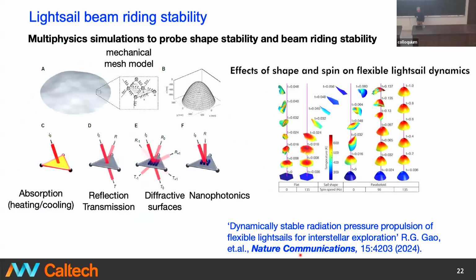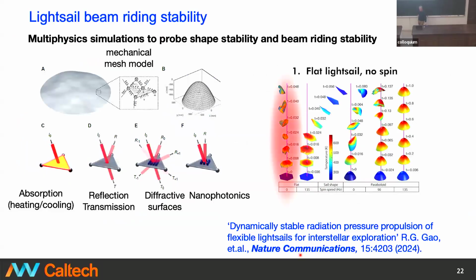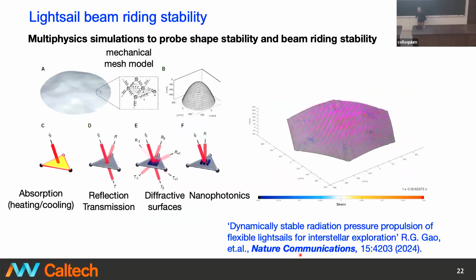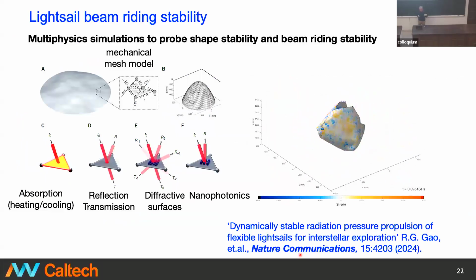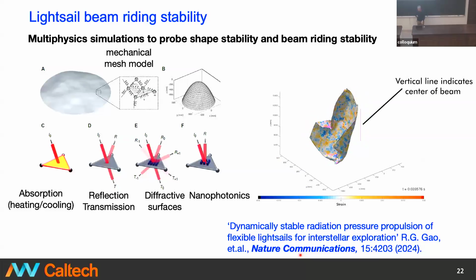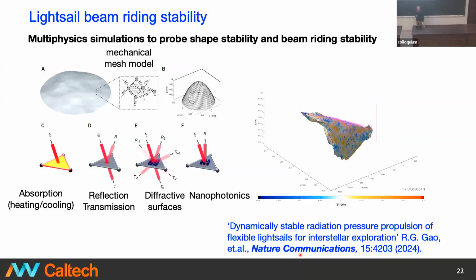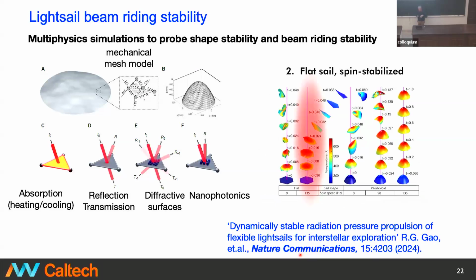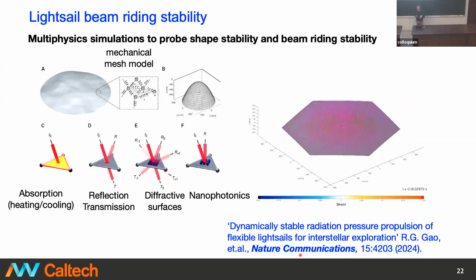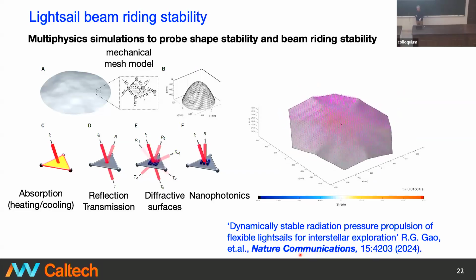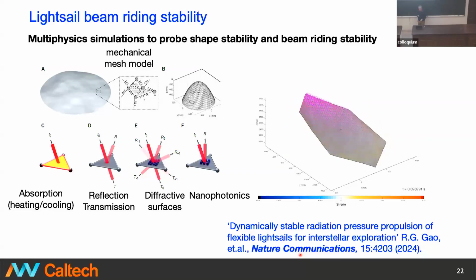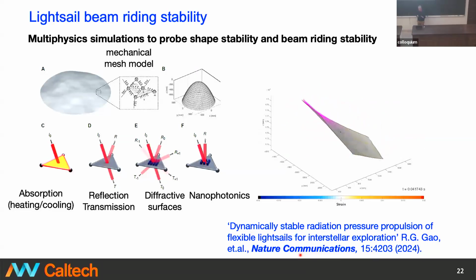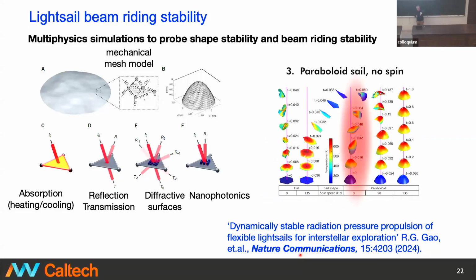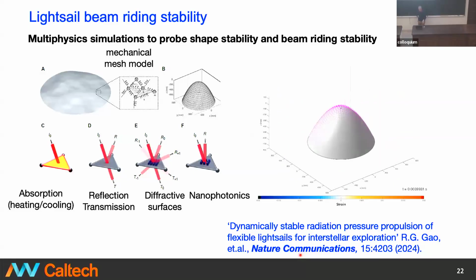So I want to say a little bit about beam riding stability. And to study beam riding stability, we developed a multi-physics simulation that takes into account absorption, reflection, scattering, and nanophotonic resonances. And of course, what we're interested in is materials that are thin membranes. And so if we simply illuminate, for example, the structure that I just showed you, or this flat structure, you can see what happens is it becomes shape unstable, and it's also beam riding unstable. It sort of veers off the optical axis.